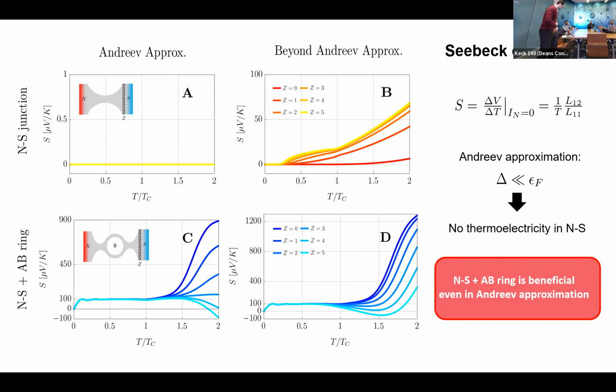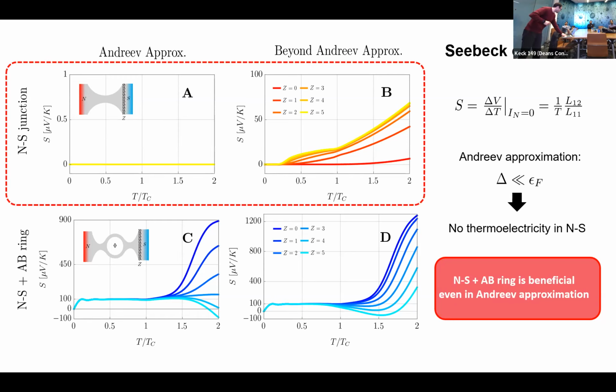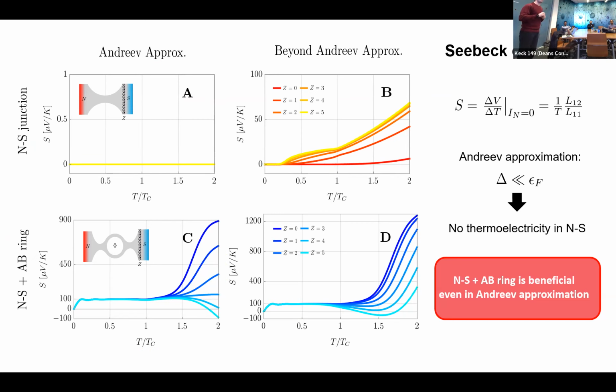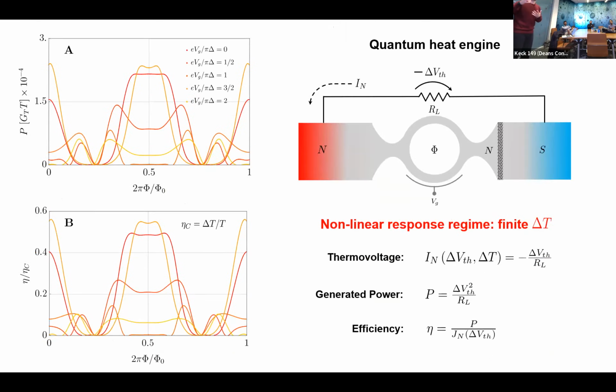Yeah, no. You're right. Okay, now the fact that we can obtain such high values of the Seebeck coefficient also inspired us to consider our system as a possible quantum heat engine, namely a system that can efficiently convert heat current into electrically generated power. And in order to investigate this ability for our system, we consider it in the so-called closed circuit configuration. Basically, we attached the terminals of our system to an external load resistance. And also here we consider the case of the non-linear response regime. So we are applying a finite thermal gradient, and by applying a finite thermal gradient, the system will respond with a finite thermal voltage delta V.